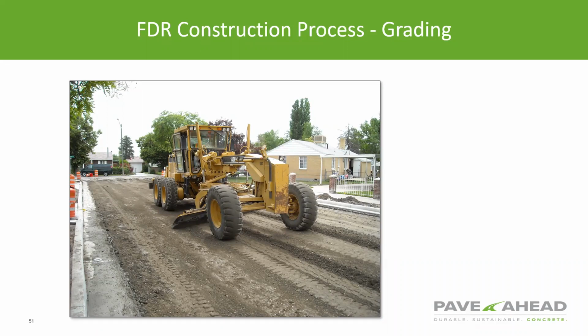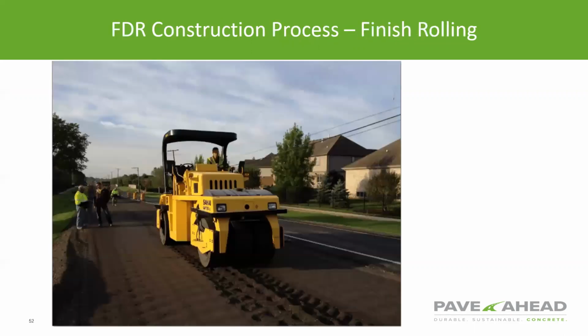Some specs are like 4 hours, but the tighter you can keep that, if you can get it done in a half hour, you're going to have a better product than if you get it done in an hour and a half. And an hour and a half should be better than if you get it done in 3 hours. So the tighter you can keep that time frame, the better the product is going to be in the end. So not getting strung out too far, keeping everything together, obviously with a competent team that can handle it, will always give the best job possible.